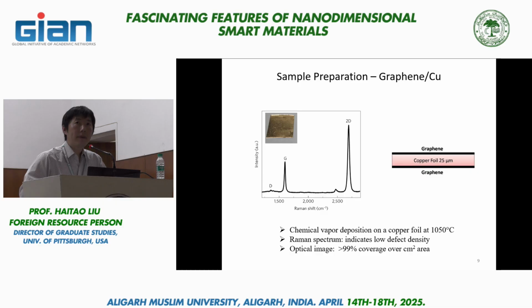So as you may imagine, I don't want my undergrad students to risk their eyeballs to do this experiment, so I have to think of something different. My collaborator came up with the wettability measurement. Now if you go back to look at the data here, people already measured the wettability of graphene, which is around 90 degrees. And for copper, if the copper is clean, the wettability is around 20 to 30 degrees. So it's a very obvious change of wettability.